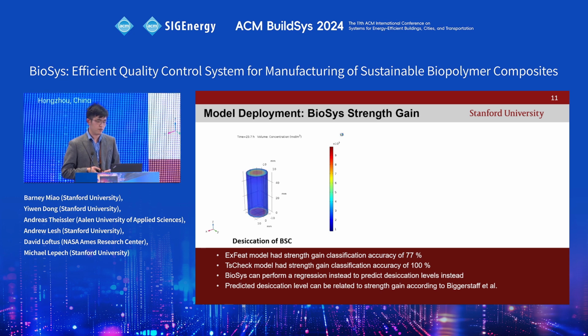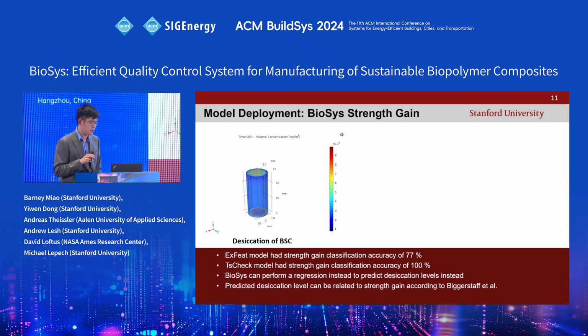but this is not really convenient for samples that are too large to weigh, or if they're in a specific dimension where you can't weigh them either. So in order to solve this issue, the BioSys system can also be used for strength gain monitoring. The image shown here is a computational model showing how desiccation occurs, and you can see a drying front, or crust, forming and shrinking continuously into the material.